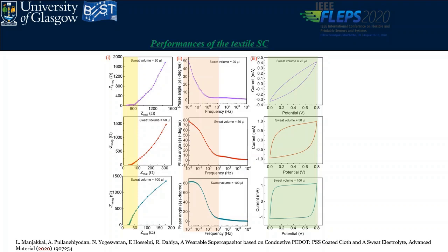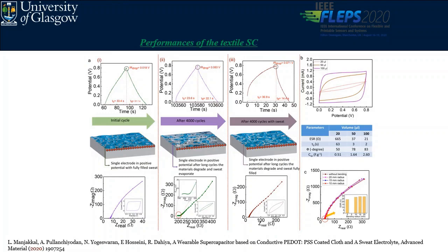And similarly, you can see the phase angle. Phase angle is directly related to the capacitance. For an ideal capacitor, the value should be almost 90 degrees. At a sweat volume of 20 microliter, the phase angle is around 50, and when increasing the volume of the sweat, you can see it almost reaches 80 degrees. And also with increasing volume, you can see the cyclic voltammetric pattern, and at 100 microliter it shows excellent performance.